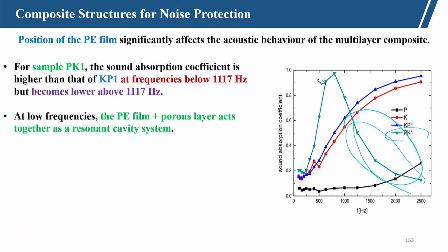At low frequency, the polyethylene film kept at the front and the porous layer act together as a resonant cavity system.